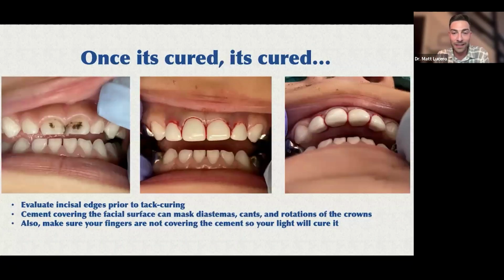And then one thing to be mindful of, and this happens to all of us at some point or another: you're holding the crowns on, you think everything's aligned. There might be a little bit of excess cement on the facial of the crown covering your vision. The pads of your fingers might be covering the incisal edge a little bit. You don't see that it's canted one way or the other. But once you tack cure that crown into place, that's it. You got to go with it, or we got to remove the crown and start from scratch. You can't move them at that point, like I mentioned, because you're going to break those polymers that have already developed. And then you're going to have less bond strength because you're breaking the polymers.